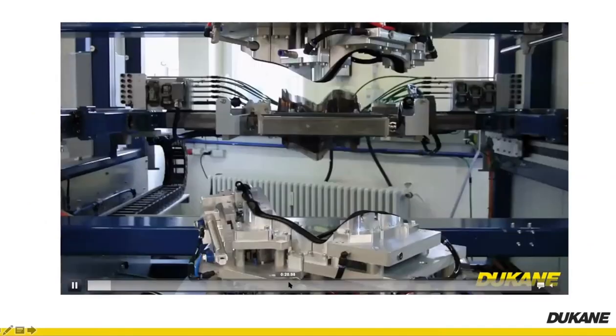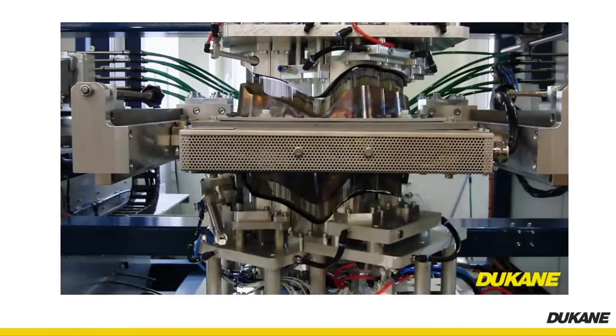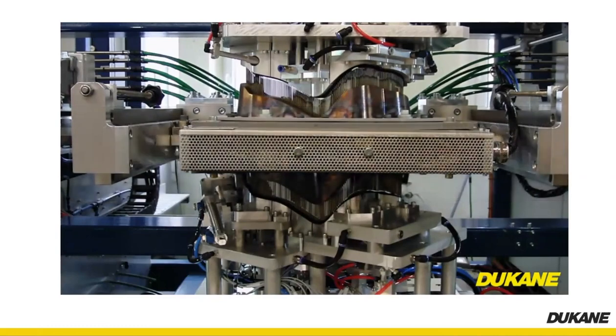Here we go, maybe. Okay, so you can see the heater coming forward, but instead of seeing IR bulbs or a plate, you're seeing lots of little needles. So what we're doing is we're passing superheated nitrogen through these needles, producing a laminar flow to melt a very complex weld seam, as you can see here.